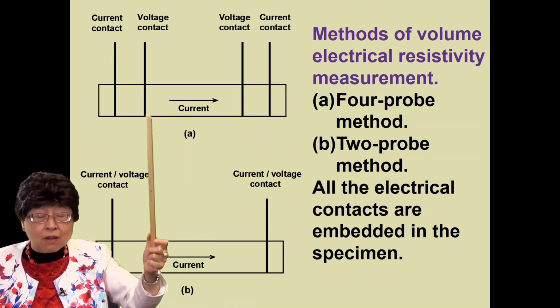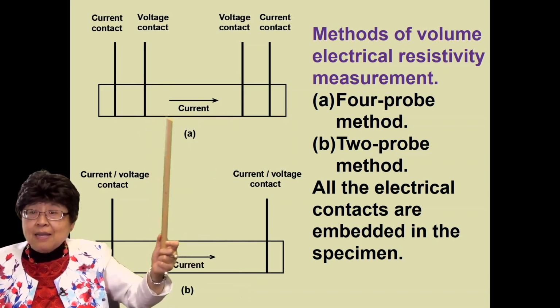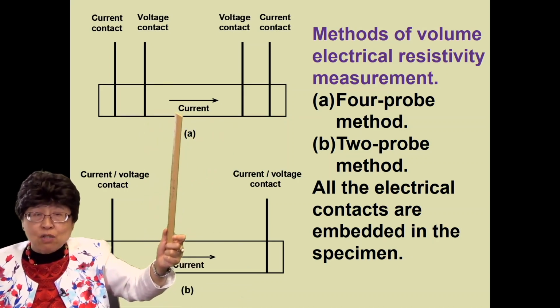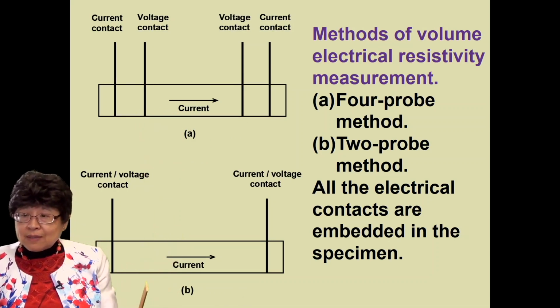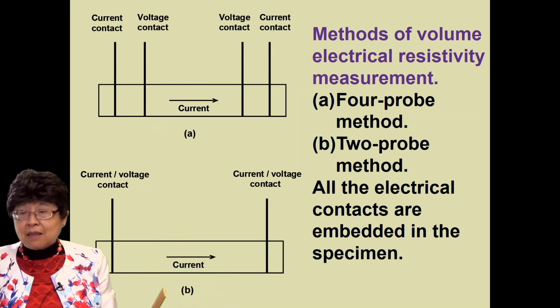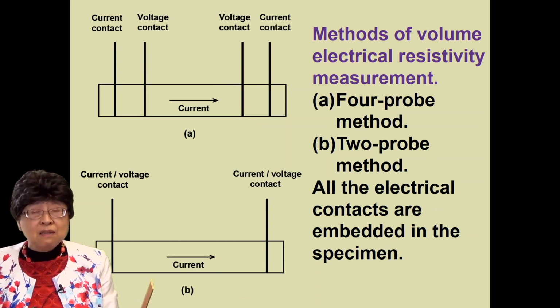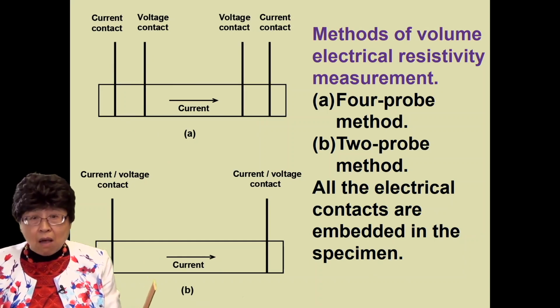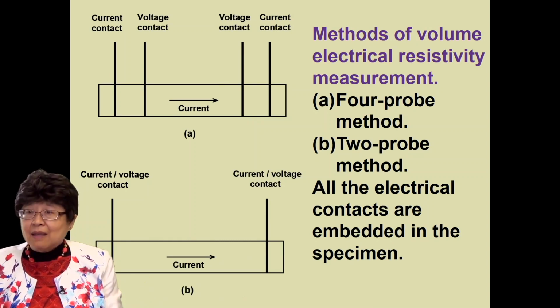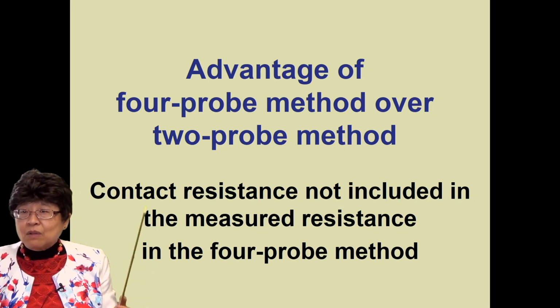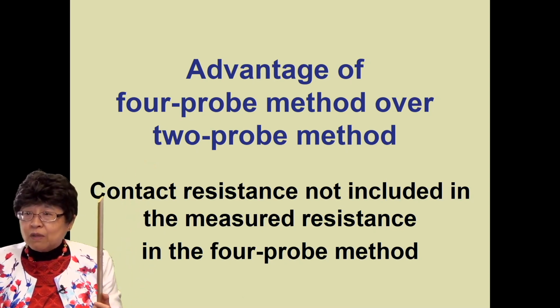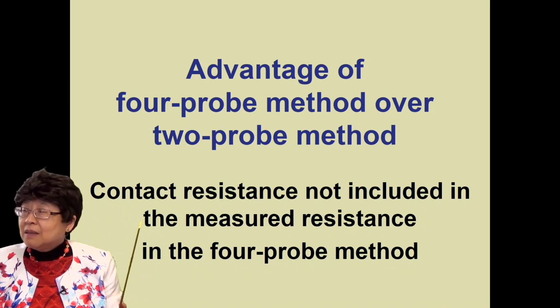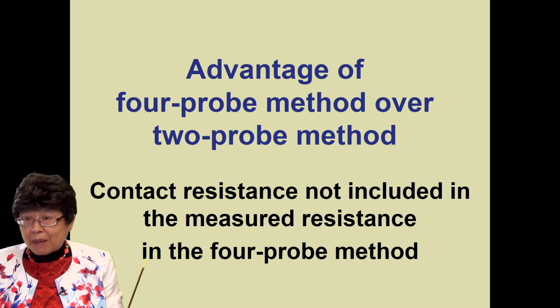Every contact has a contact resistance. You don't want to include that in your measured resistance because it's the specimen resistance that you're after. Now, if you instead use only 2 electrical contacts, then the measured resistance would include the contact resistance along with the specimen resistance, and that can be very wrong. So the main advantage of the 4-probe method over the 2-probe method is that the contact resistance is not included in the measured resistance.